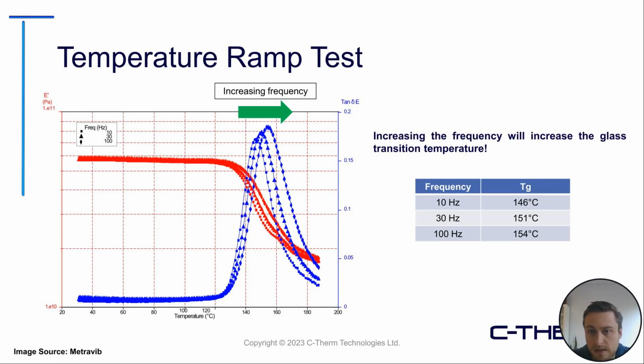We can see here that increasing the frequency will increase the glass transition temperature. I have them listed on the right here. I should note too that this increase in frequency or glass transition temperature will be slightly different for each material, but this is a known phenomenon: if you increase your vibration frequency, you will increase your glass transition temperature, which is really important to consider for damping as well, where we're really focused on maximizing the damping for our application.